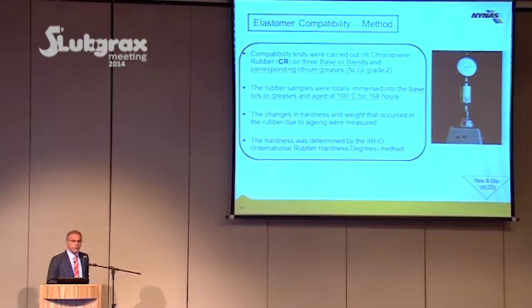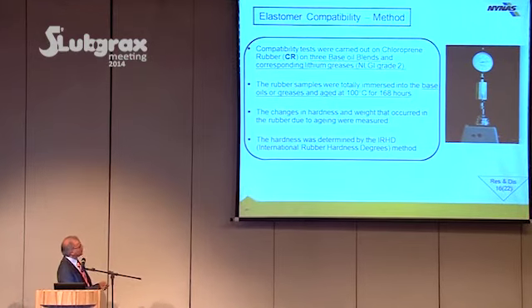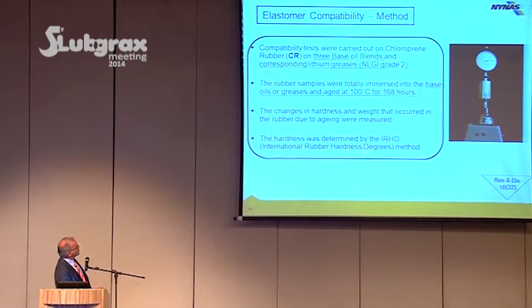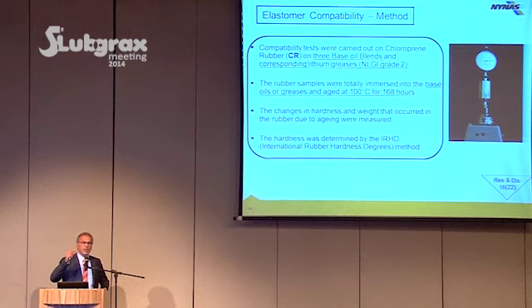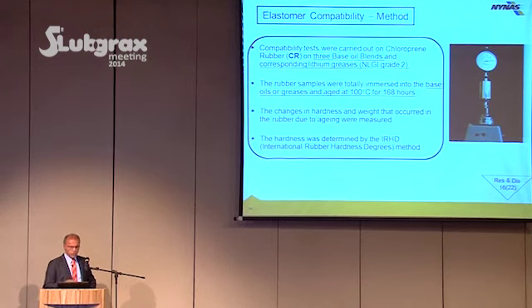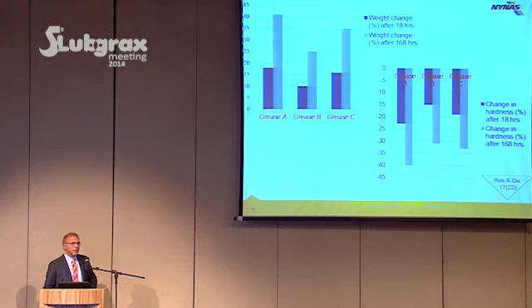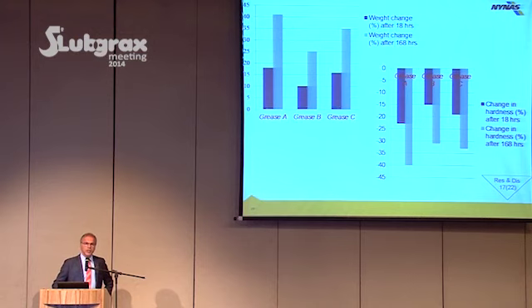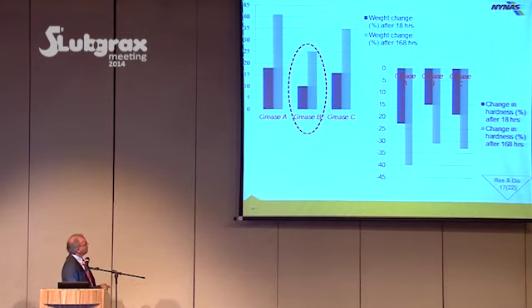One of the test methods which is recommended and is used is called International Rubber Hardness Degrees. What you do, you immerse rubber into the oil or grease for 168 hours, meaning a week, at 100 degrees C. After a week, you wash it out, you clean the rubber, and then you measure the hardness, the weight change, the glass transition temperature changes, and so on. So what we did, we also initially measured these numbers. We have done it after 18 hours as well as after a week for all three greases.